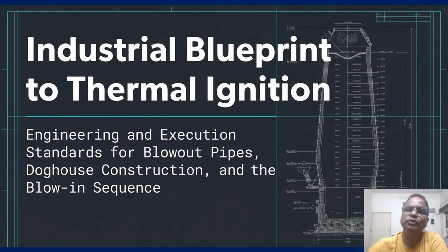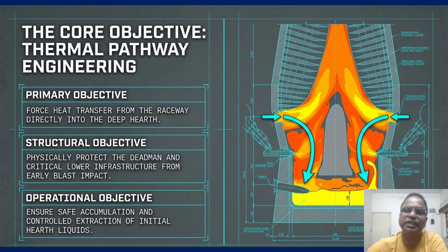So coming to the thermal pathway engineering. Look at the thermal map on the right. You will see the furnace profile with the bright arrows indicating the hot blast entry point, the tuyeres. Notice the large orange to yellow clumps of heat, that's the raceway. The primary objective, as stated in the top left box, is to force heat transfer from that raceway directly into the deep hearth using our pipe as a bypass channel.